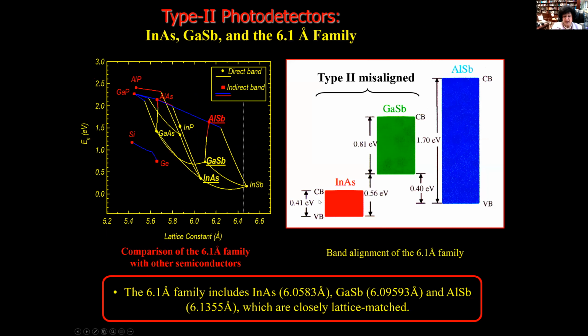So here I'm showing you now, you have here, again, the indium arsenide, gallium antimonide. As you can see, the conduction band of indium arsenide is at lower energy than the valence band of the gallium antimonide. So if we put them together, we have the separation of the electron and hole. And we have aluminum antimonide, large band gap, that you are going to see we are going to use as band gap engineering to go from deep UV up to THz.